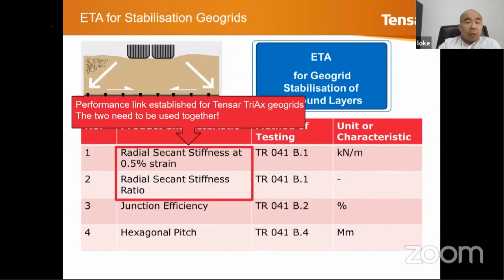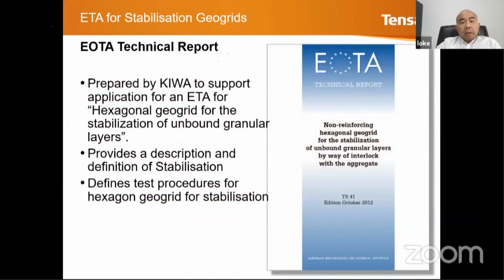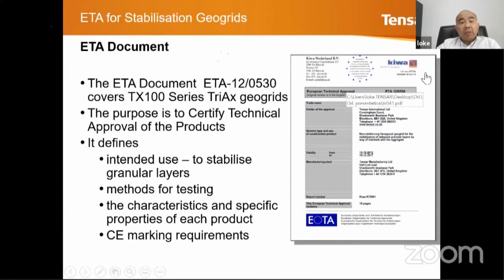So these two go together, they are tied together, you can't separate them. And the same thing here, you need to have high junction efficiency. And the other one is the hexagonal pitch, which is basically the size of the hole, or the aperture of the geogrids. And there are documents already established by the European Organization of Technical Approval, which spell out the description and definition of stabilization. Very clearly, you can see that it's a non-reinforcing hexagonal geogrid for the stabilization of unbound granular layers by way of interlock of the aggregates. And there are test procedures already given in this document. And there are also certifications. This is a Kiwa certification, which defines the intended use, which is to stabilize granular layers, and the method of testing, and also what are the characteristics and the properties that give you that performance.